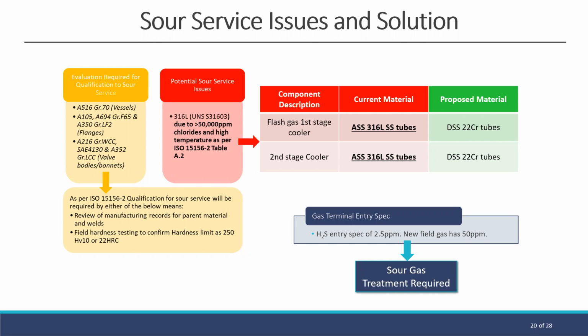We do, however, have a CRA component that is 316L. That is a potential issue here, and this is due to the high chloride concentration, which makes it susceptible to SCC. Of the topside components, there are two items that have 316L as a material. That is the tube bundles of the first and second stage flash gas coolers. Therefore, we would recommend that these are changed out for a less susceptible material such as a duplex stainless steel.